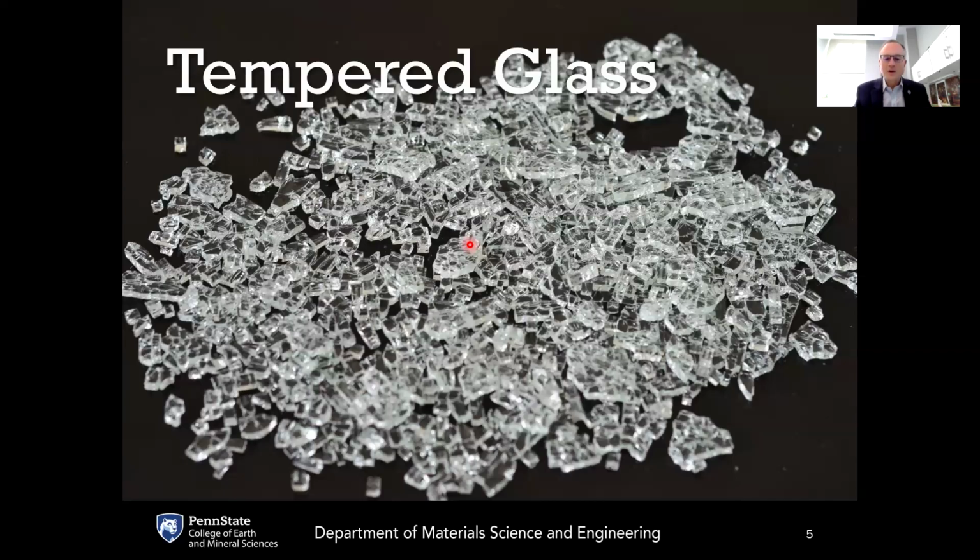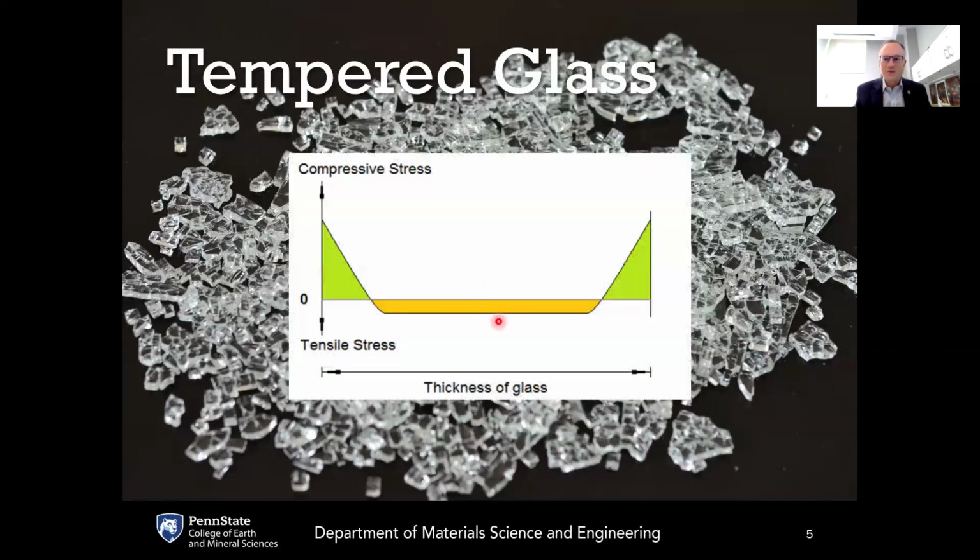And if there's a greater amount of tensile energy that gets released, which would come from having a greater amount of compressive stress, and that requires that balancing by the tensile stresses, that greater amount of tensile energy translates into a greater degree of acceleration, which means that the crack tip is going to accelerate more rapidly and reach its terminal velocity sooner. The terminal velocity of a crack tip in a typical silicate glass is about 2,000 meters per second, and this is governed by the speed of sound in the glass.